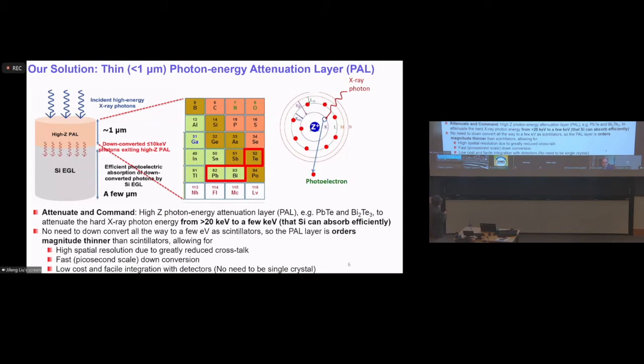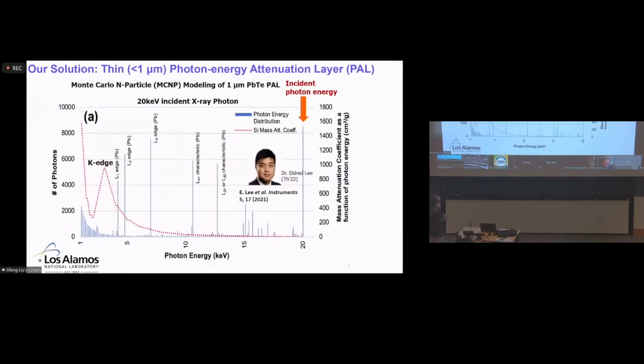And also you don't need to use single crystal, because essentially you're counting on the atoms' resonance. You don't care so much about defects in the materials. No need to use single crystal, you can directly deposit. And also this scattering process, basically the energy down conversion process, is due to photoelectron generation and Compton scattering. Those are much faster than what you get in the luminescence in the visible regime. So it can potentially get into picosecond scale in terms of time resolution.